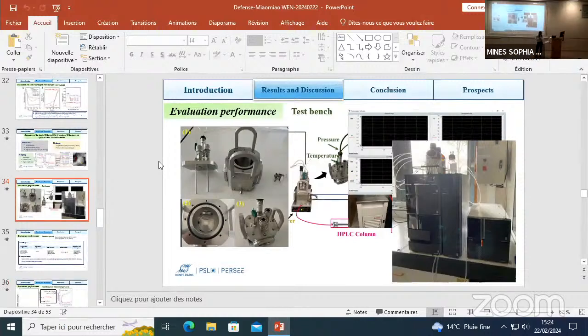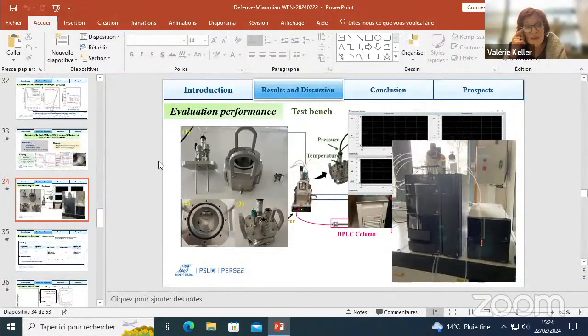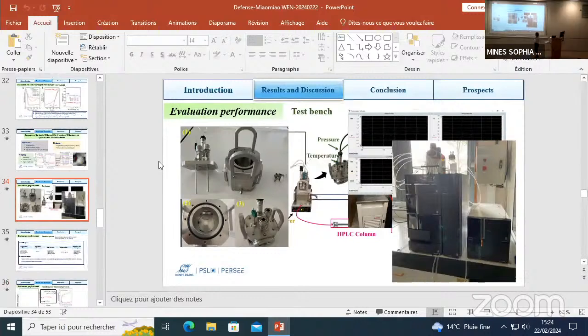Actually, no. It should be done, to make sure which carbon is getting reduced. But the reaction I was doing didn't distinguish which carbon is getting reduced, from sodium carbonate or CO2 bubbles. At the beginning we didn't do it, and one day we did it, and we were very surprised that we could produce carbon-based compounds without feeding CO2.